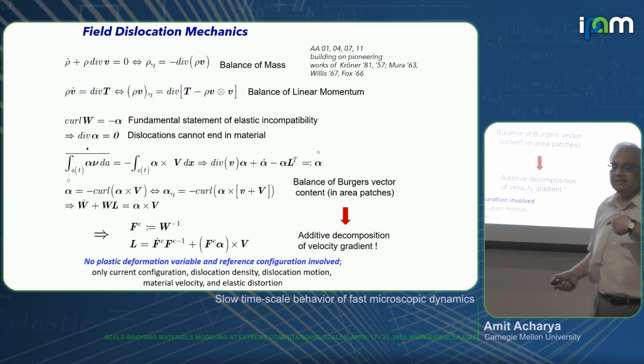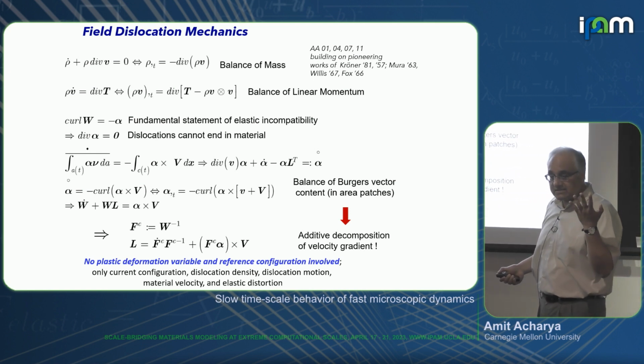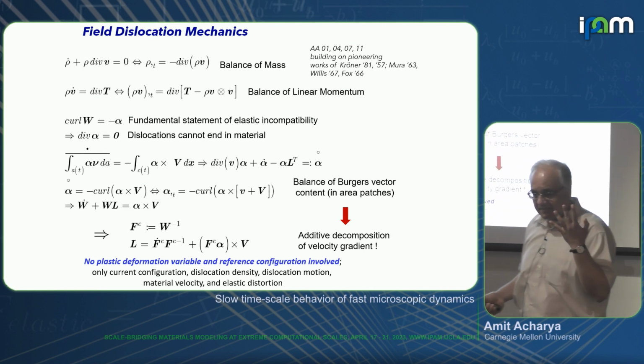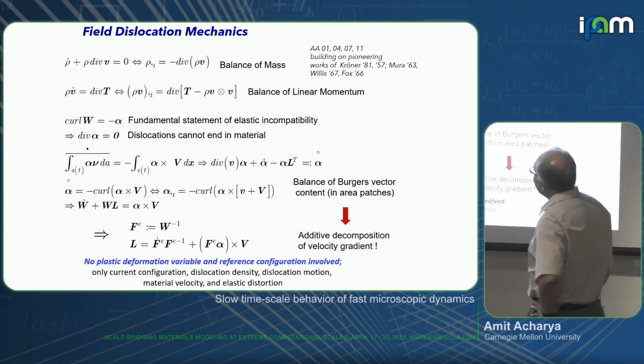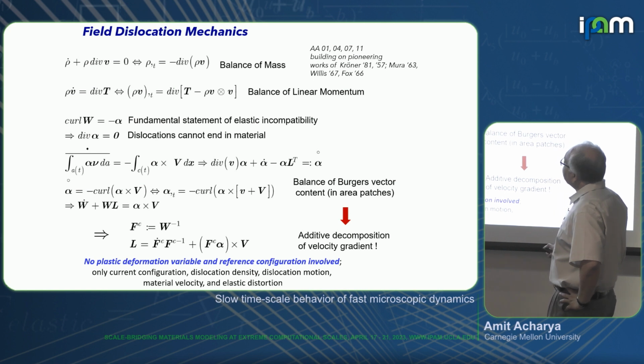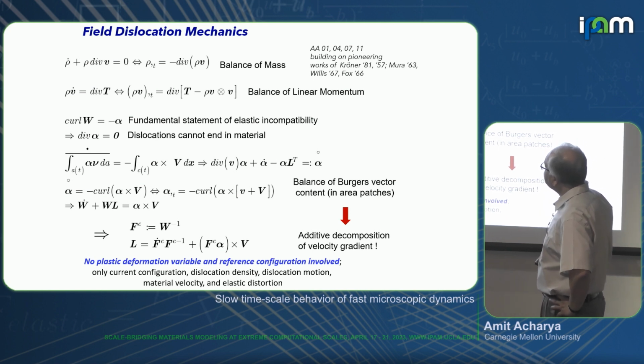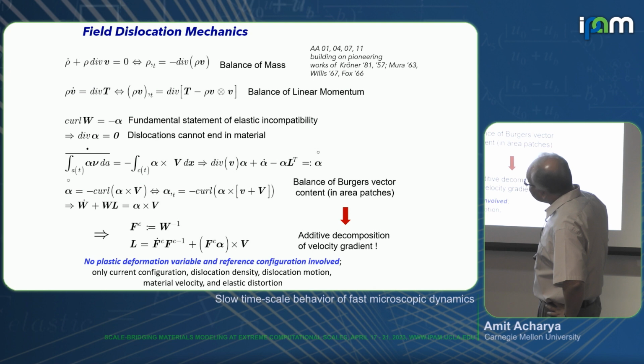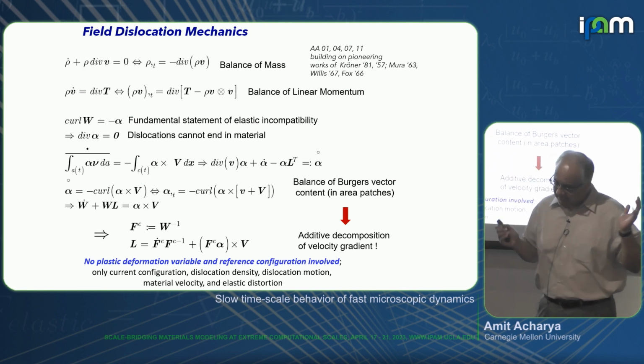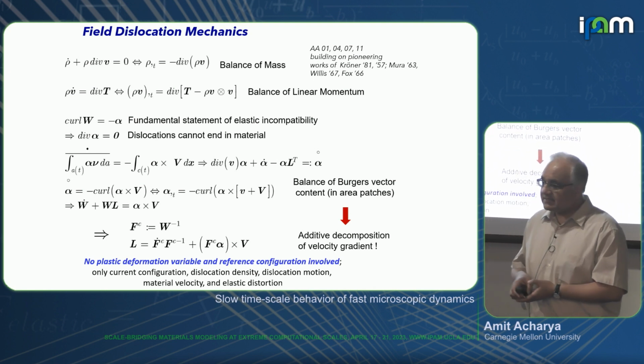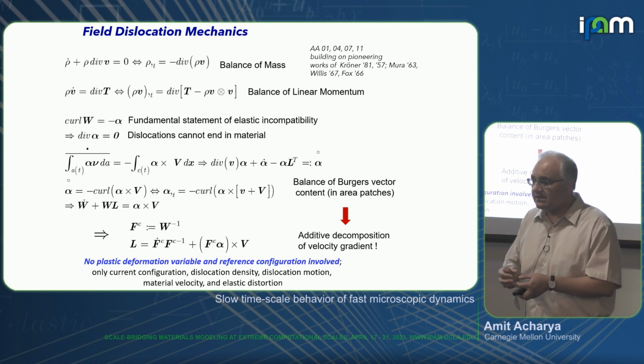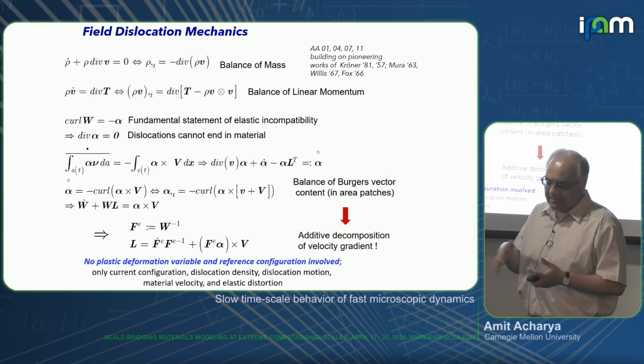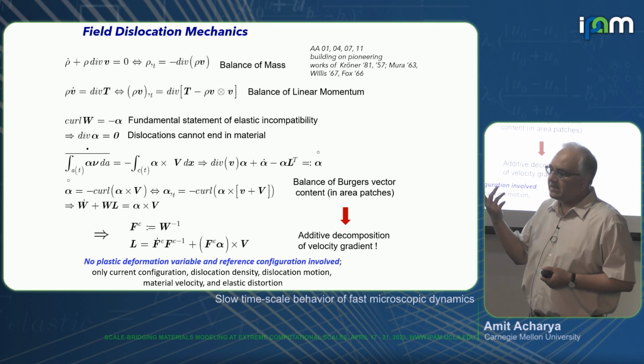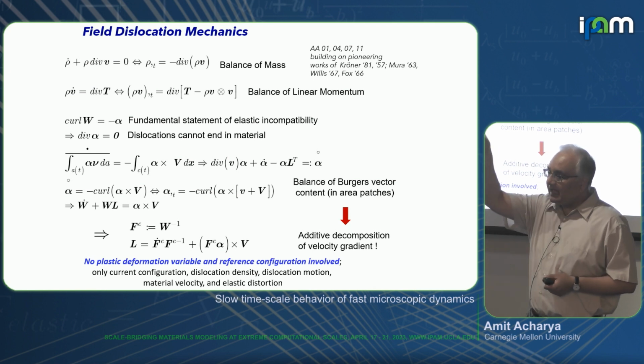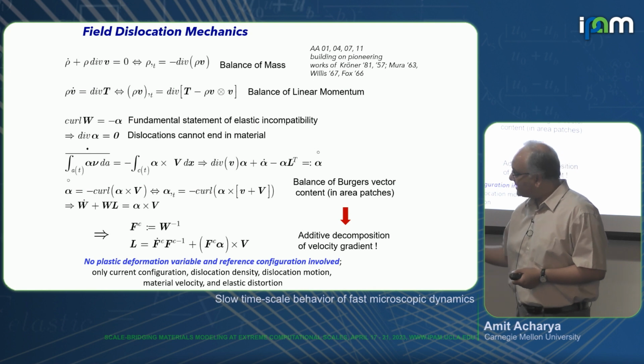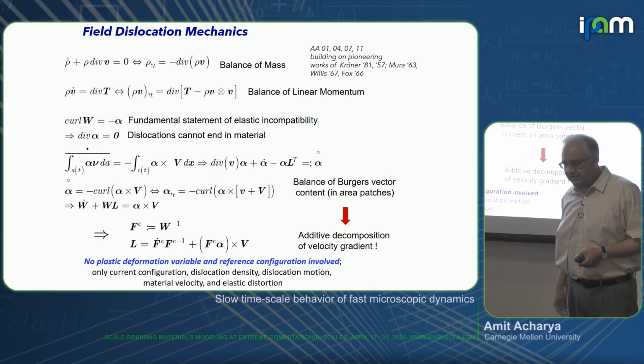The difference between elasticity and this is that the inverse elastic distortion has a non-zero curl. It's not a gradient anymore. And what it is called is the dislocation density. So if it's a curl, then div alpha, of course, has to be 0. And the evolution equation for alpha is not something you make up, whatever, but because it's defined locally as a curl, you can rationalize this. This carries a Burgers vector charge. If alpha were to be localized in a tube, this would carry a topological charge because of its definition.